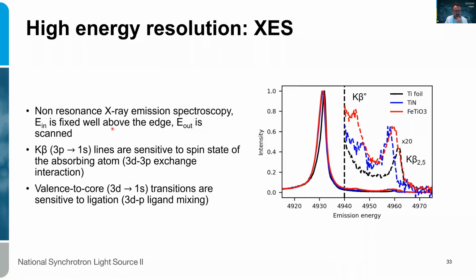The other early demonstration experiment was getting those very weak K-beta satellites, the K-beta 2,5 and K-beta double prime, which are very, very sensitive to the neighboring ligands, because there is a mixing between the 3d levels and the ligands. In this case, you can see how you can discriminate between the nitrogen and the oxygen in the coordination sphere of titanium from measuring, again, these very weak transitions. So how is it done?